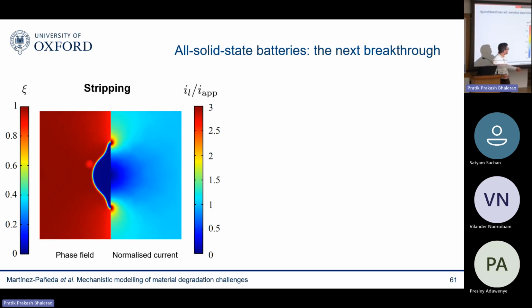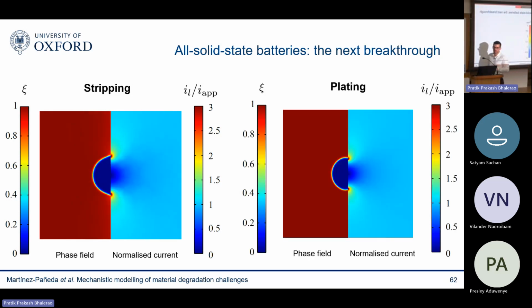And you can see how not only the model captures the expansion of the void, looking similar to the SEM images that I showed you before, but also how the current localizes at the void edges. And therefore, you naturally capture those corrosion currents. We are not putting in any criteria. We're just solving the coupled problem. And the model tells you, oh, you have a lot of current down there. And when you do plating, it's the opposite effect. You are depositing lithium, and the model is able to capture how the void diminishes in size, how those hotspots eventually disappear, and how you eventually even get the occlusion of that void that we saw in those macroscale experiments.